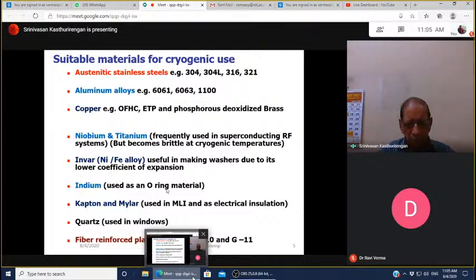Titanium is a very tough material and also lightweight, so they are used. For example, niobium is used for superconducting RF systems. Niobium becomes brittle at cryogenic temperatures, but one has to design the system properly so that it doesn't become brittle. Then we can use alloys like Invar, which is a nickel iron alloy. It can be used for making washers because it has a very low coefficient of thermal expansion.